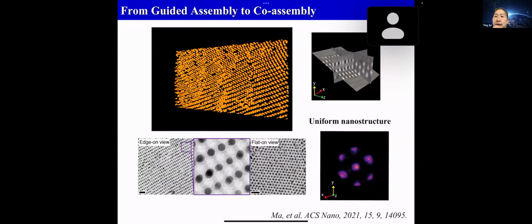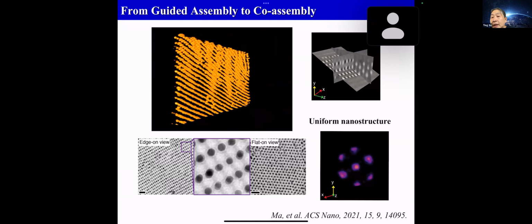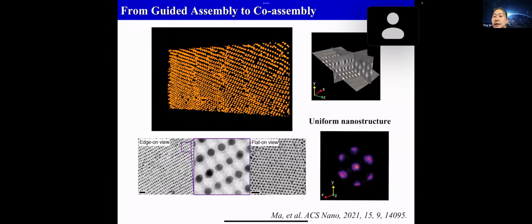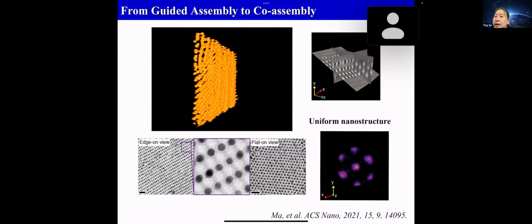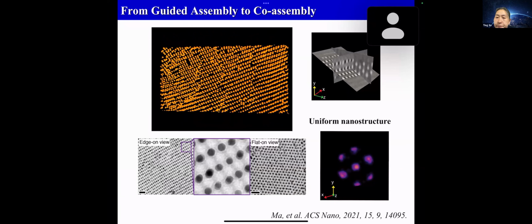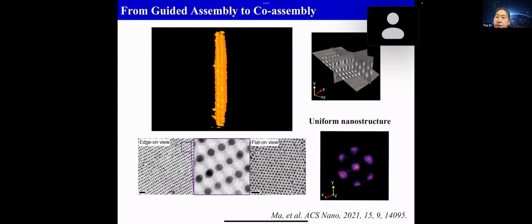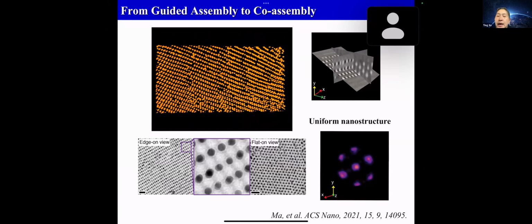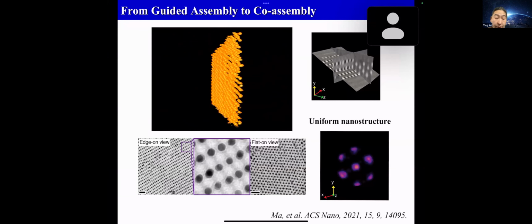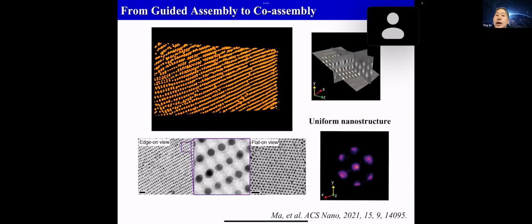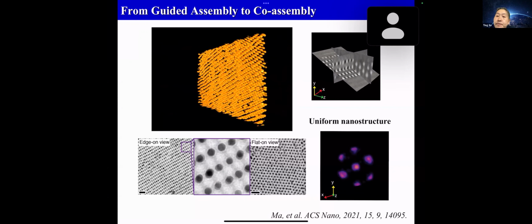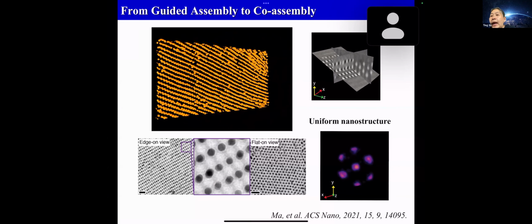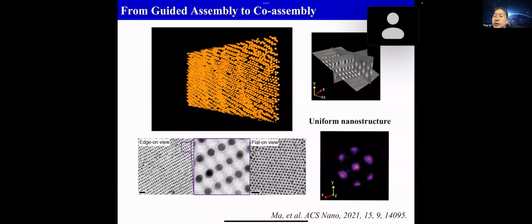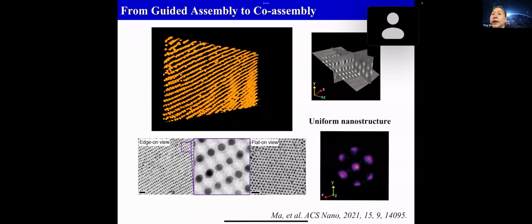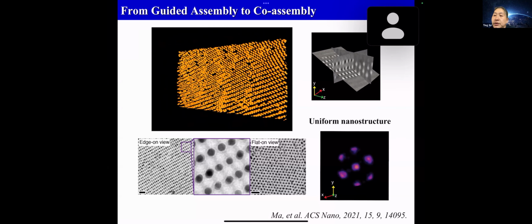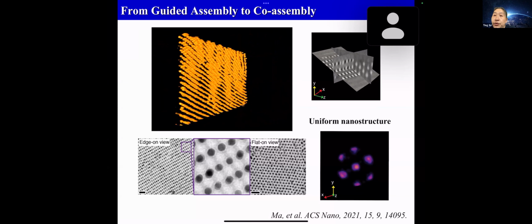So for example, this one is a lamellae, but looks like a perfect lamellae. But if you see, the nanoparticles reside in there and puncture one of the lamellae. And if you look at the interface of the particle with the organic matrix, it interacts with both components. It really suggests that the system doesn't pay a penalty for this interface between the two components that give you the microdomain, as well as the particle with either of them. And even though this is a new morphology, we did STEM tomography, and then we look at the histogram of the unit cell, you can see that the unit cell is very uniform.